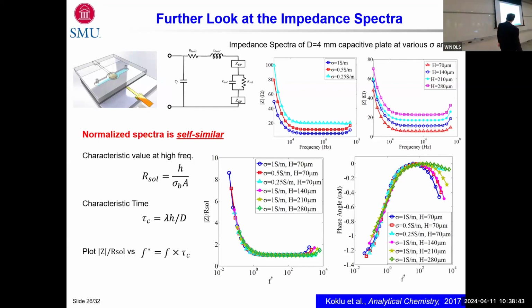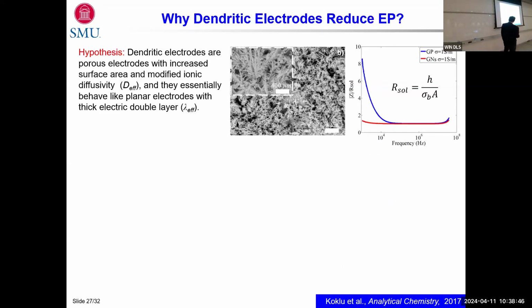Beautiful. So I could do that for a planar electrode, but then can I do that for dendritic electrodes? And if I can, what is changing? So we came up with the hypothesis. We say that dendritic electrodes are behaving as if the medium is a low conductivity medium with a thick double layer. And indeed, here is Z over R solution versus frequency obtained at 1 S/m. Planar electrodes are shown in blue, and GNS is the gold nanostructure. At the same conductivity, you can see the difference. One starts from 8 something, and the other one starts from 1 something. Obviously, their behaviors are different.